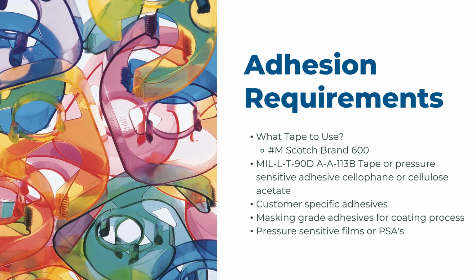A lot of times in shipping, customers, coating vendors, they're going to want to protect that film. You spend hours putting down a perfectly adhering film, everything goes great. Then you put a pressure sensitive adhesive over it, wrap it, send it away. When you send it away, you have to imagine that the wrapped optic with the pressure sensitive adhesive goes through multiple environments. When it's going through these multiple environments, temperature changes, humidity changes, all different sorts of things happen,